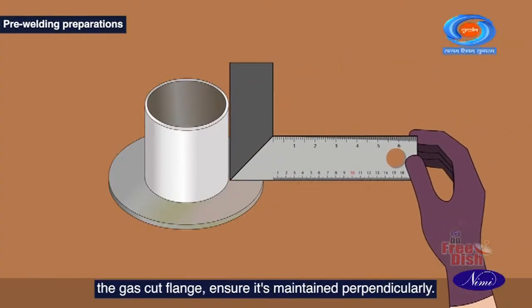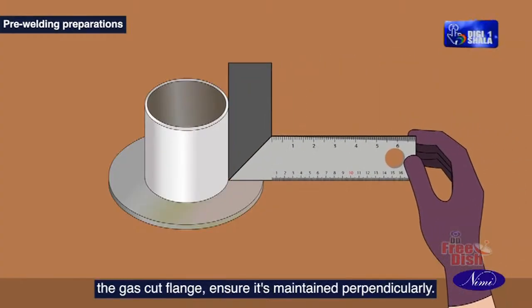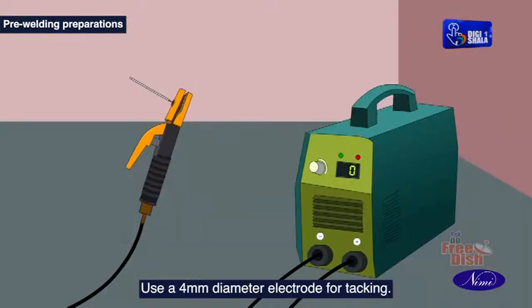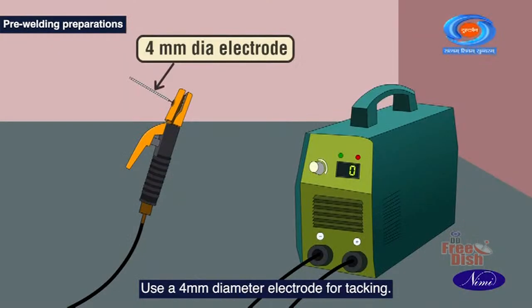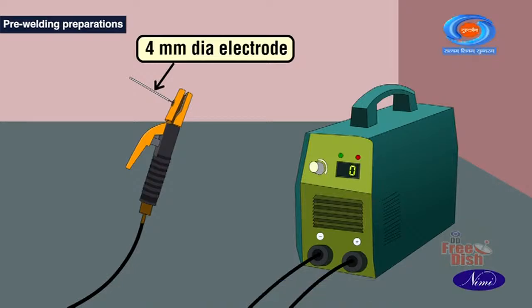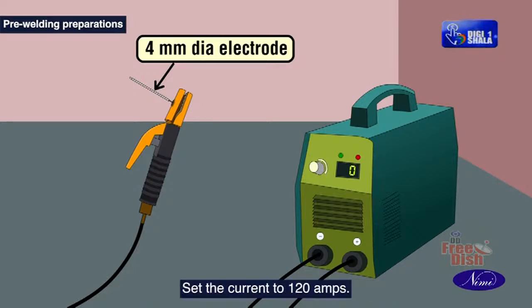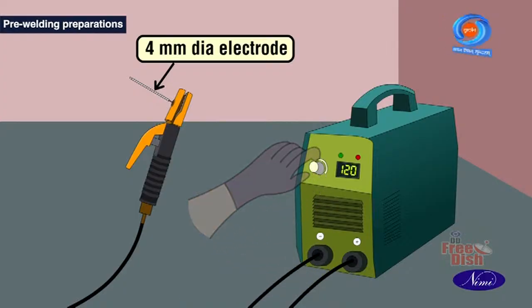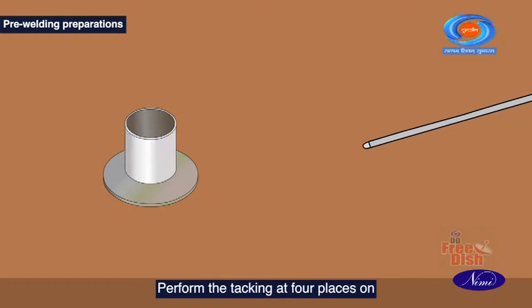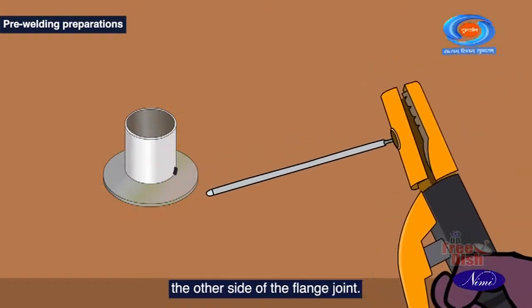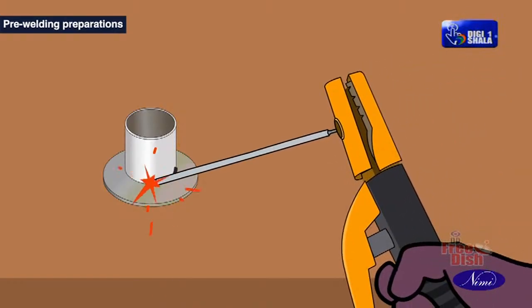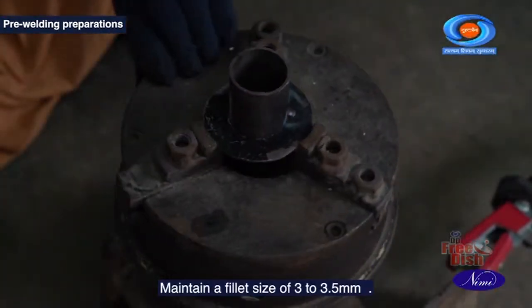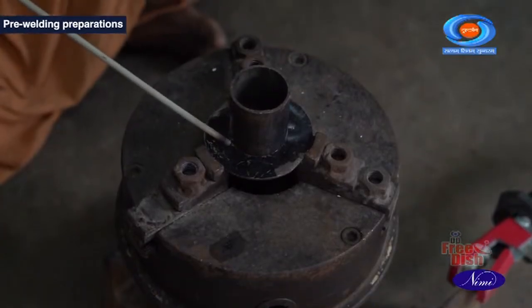When tacking the pipe with the gas cut flange, ensure it's maintained perpendicularly. Use a 4 mm diameter electrode for tacking. Set the current to 120 amps. Perform the tacking at 4 places on the other side of the flange joint. Maintain a fillet size of 3 to 3.5 mm.